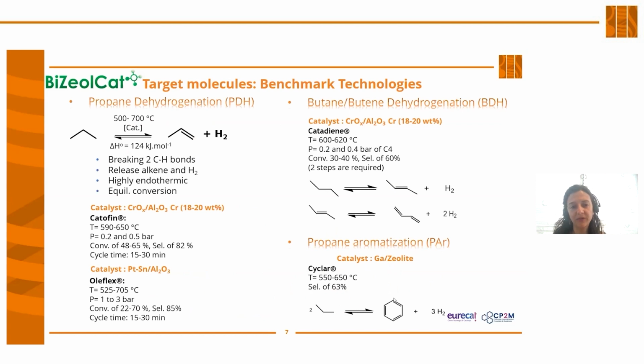It's important to remark that all these processes are equilibrium. In the case of the propane dehydrogenation, I show you two different processes with catalysts based on either chromium, with all the safety issues that it has, or platinum tin. In these cases, temperatures of the process are high, so it's a very high energy consumption. Again, for the butane dehydrogenation, we also have a chromium catalyst. And in the case of the Cyclar, it's a gallium catalyst, but again, since all of them are highly endothermic reactions, we need very high temperatures.